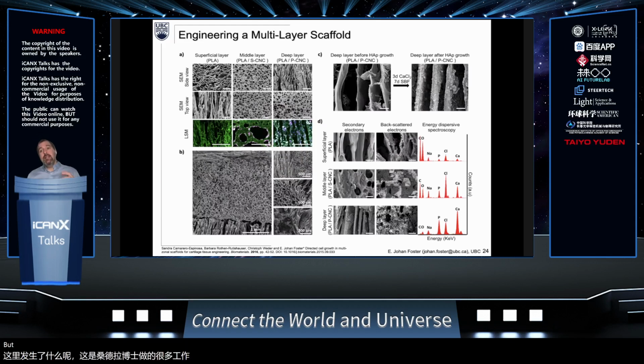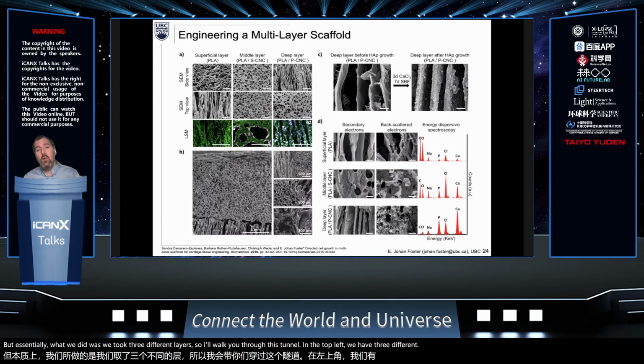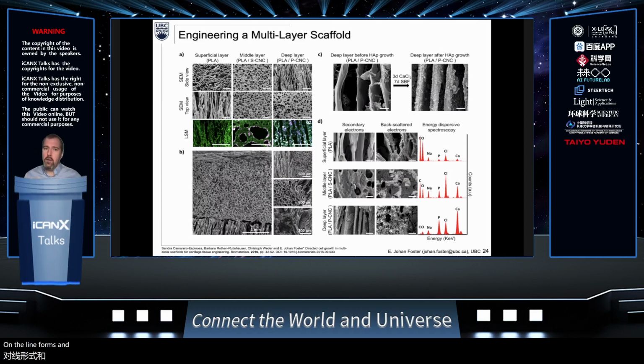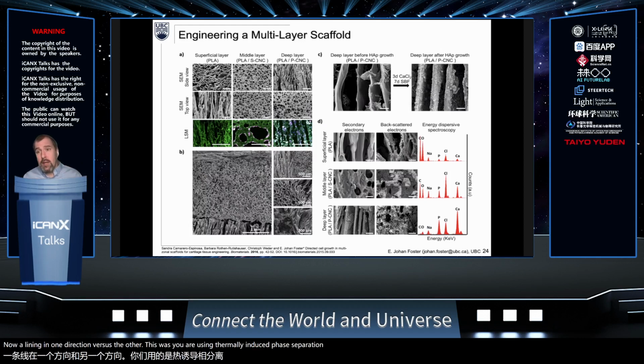But essentially what we did was we took 3 different layers. So I'll walk you through this. In the top left, we have 3 different layers. We were able to make unaligned foams and aligned foams. So mimicking that deep layer, the middle layer, and the superficial layer. Now, aligning in one direction versus the other, this was using thermally induced phase separation to give an elongated structure.